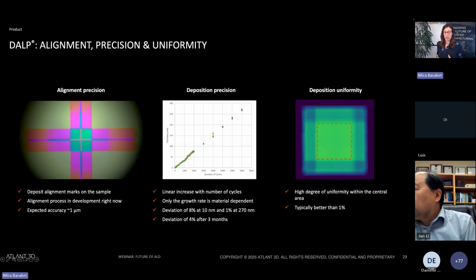So of course, this is dependent on what material you are depositing, what substrate you are depositing on, and the nozzles that you are using. So these numbers are only for one material with one same nozzle used all at the same time. In terms of the material uniformity, we also have a high degree of uniformity of the deposited material, and we are typically better than 1%.